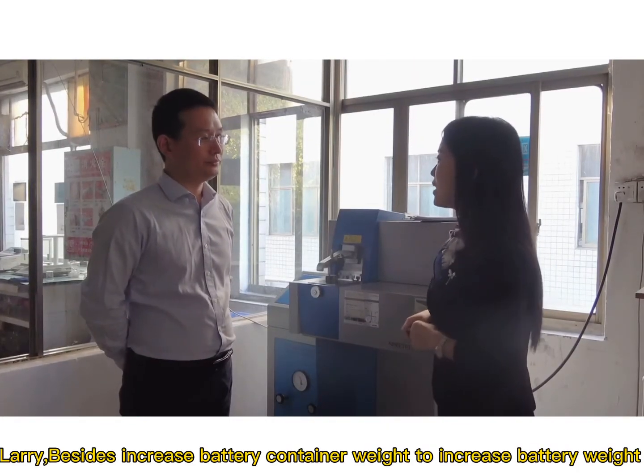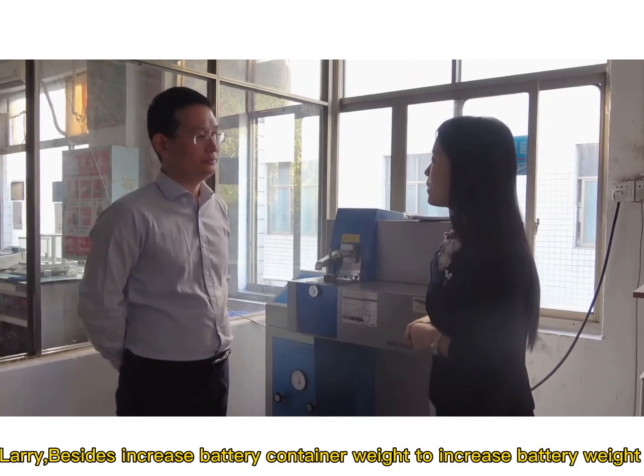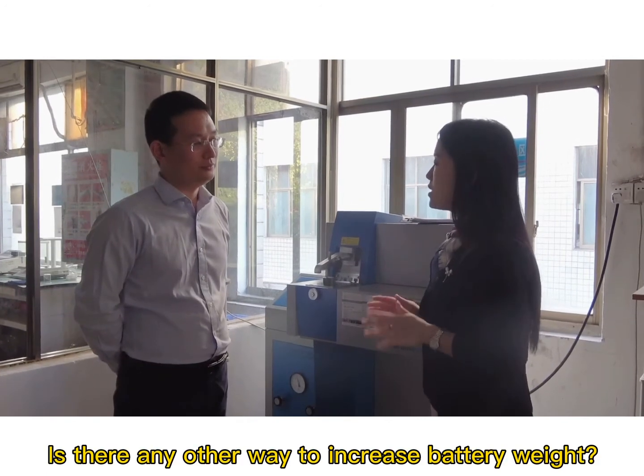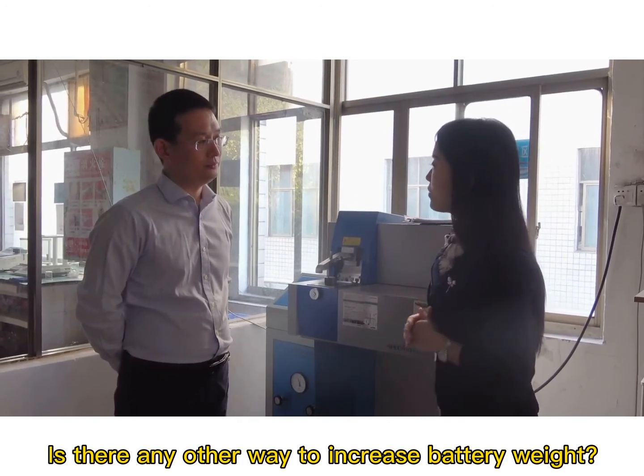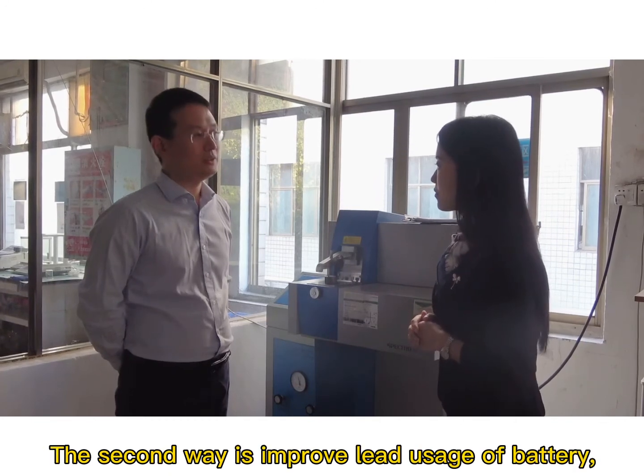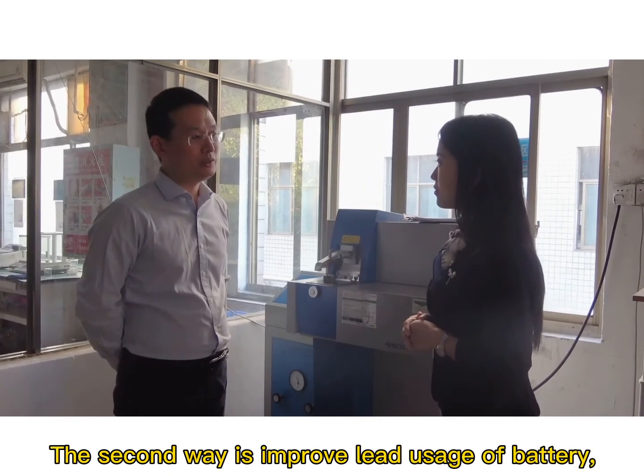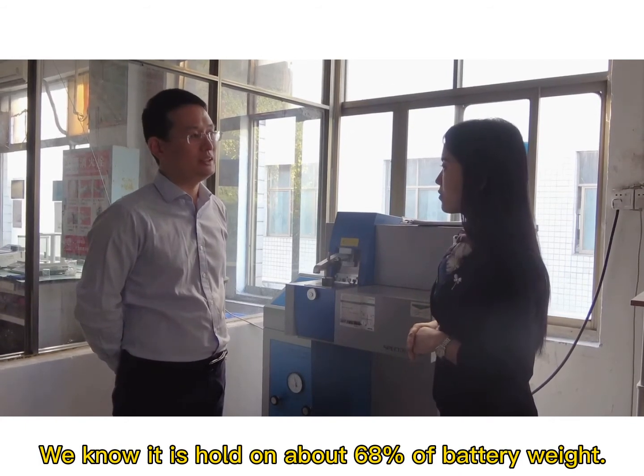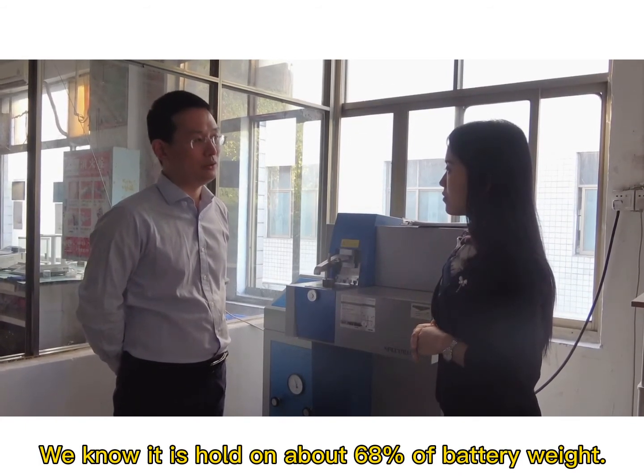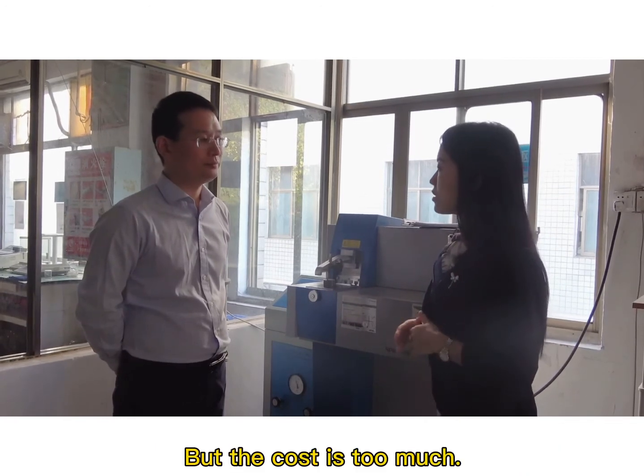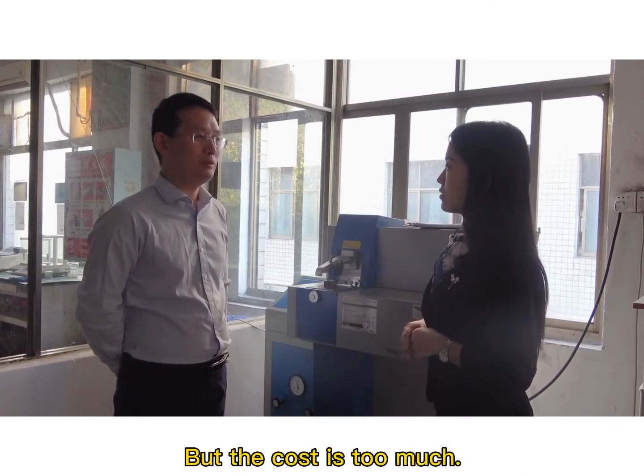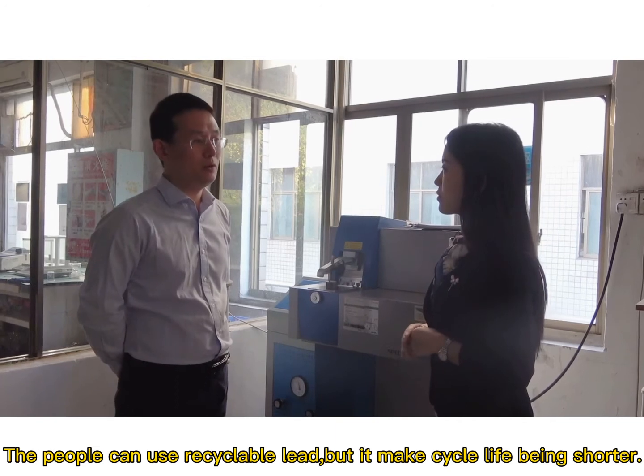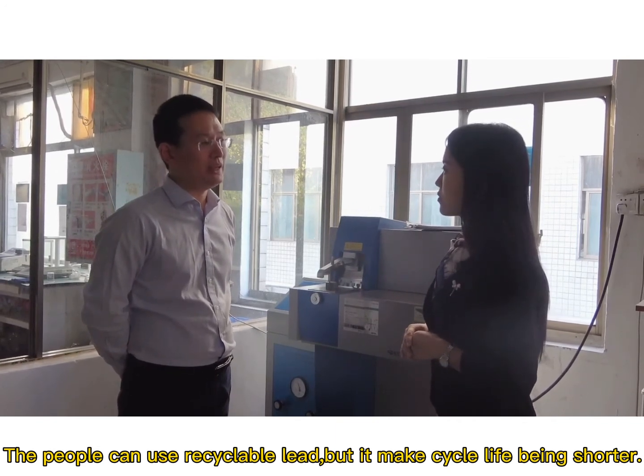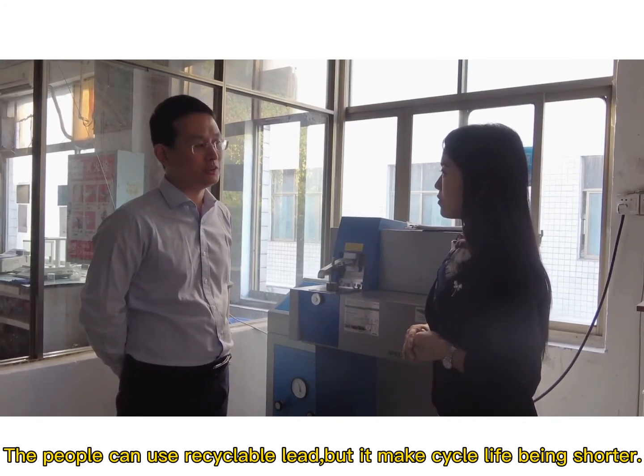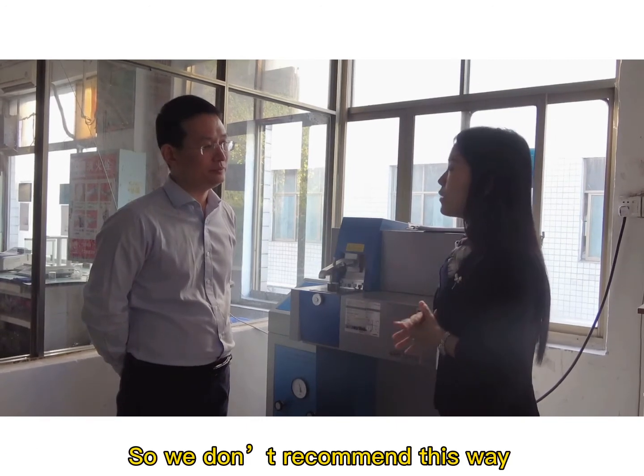Besides increasing the battery container weight, Larry, is there any other way to increase the battery weight? Yes. The second way is to increase the lead usage in the battery. We know it makes up about 68% of the battery weight. But the cost is too much. People can use recyclable lead, but it makes the cycle life shorter. So we don't recommend this way.